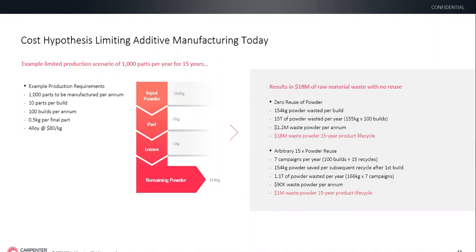Now, if you factor in an arbitrary situation where you're able to reuse the powder 15 times, your numbers actually go down significantly, where you are essentially saving 154 kgs of powder per subsequent recycle after the first build. So essentially, instead of wasting 15 tons of powder every year, with the number of recycles that you have in there, you're only wasting about a ton of powder, which essentially translates to about $1 million of powder wastage over a 15-year product life cycle. So figuring out when your powder goes out of spec and optimizing the number of reuses that you can achieve out of a given powder sample is extremely important.